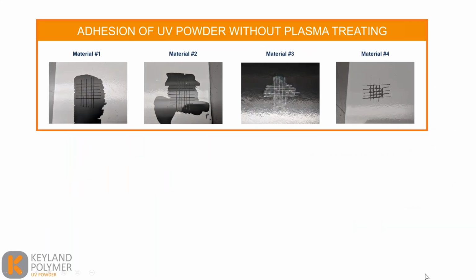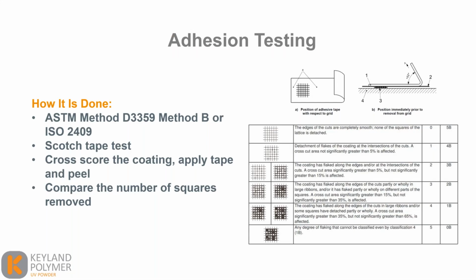So how do we test this? We use the standard ASTM 3359 method B, where a series of lattice cross marks are cut into the film down to the substrate. Many of you are probably familiar with this. Pressure sensitive tape is applied. It's then removed, and the amount of material removed is what is used with the graph on the right to judge the loss of adhesion.